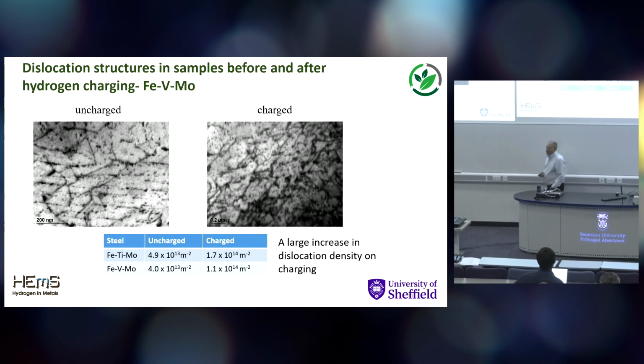So we can see roughly the difference in material behavior when it's charged. But there's some other very interesting things that happen that are perhaps a bit surprising. TEM image on the left when it's uncharged, on the right when it's charged. The first thing that you see is there's an increase in dislocation density in the material. Really rather surprising, but it's not just a small increase. The values here, if you can read them, it goes up by an order of magnitude or so in the dislocation density, just from hydrogen charging. We've not applied any stress or anything like that. Simply from the charging, the dislocation density has gone up a lot.